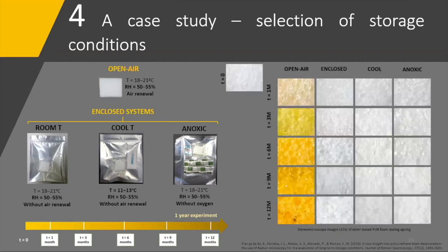From the stereo microscopy images that you can see here, it is possible to observe that along the dark aging experiment, the samples kept inside barrier film bags, identified here as enclosed, cool, and anoxic, remained white through the entire aging. In contrast, open air resulted in drastically yellowed samples, already visible after 1 month in the dark. Then, from the use of Raman spectroscopy, even though all these enclosed systems proved to minimize color changes, anoxic and cool storage were the ones showing the best results in relation to the prevention of molecular changes, as fewer spectral variations have been detected for these two cases.